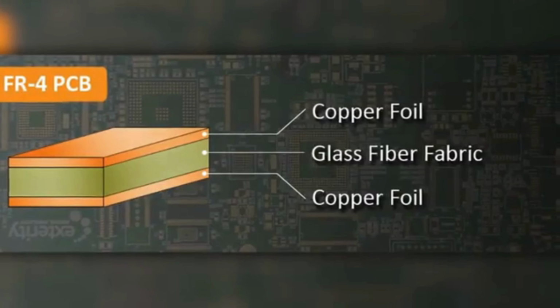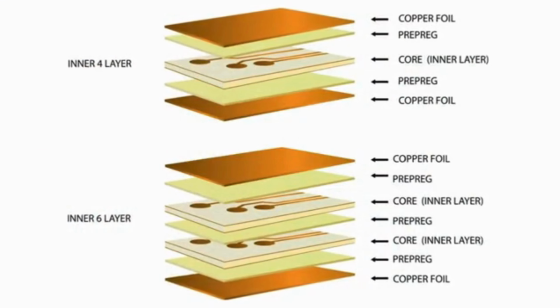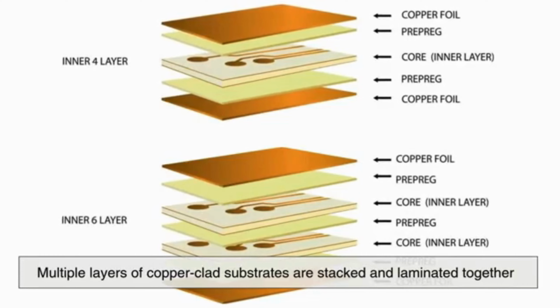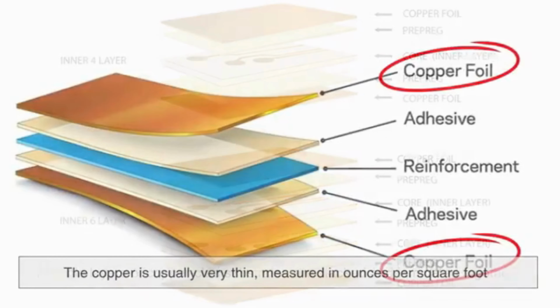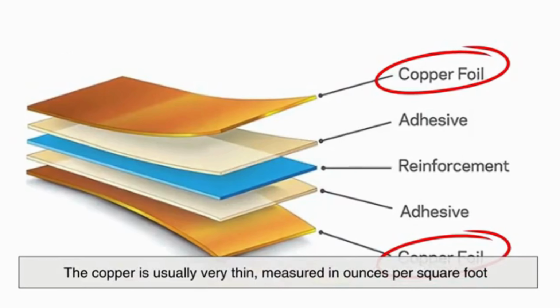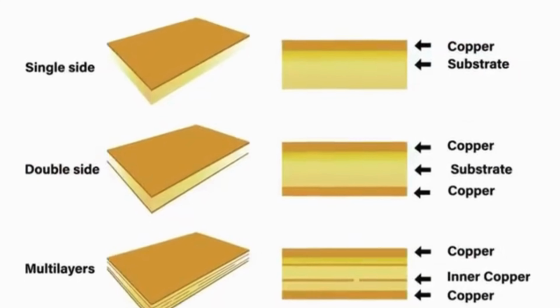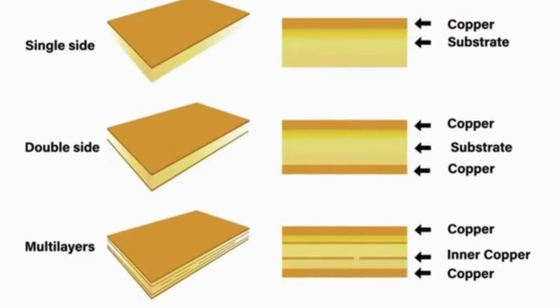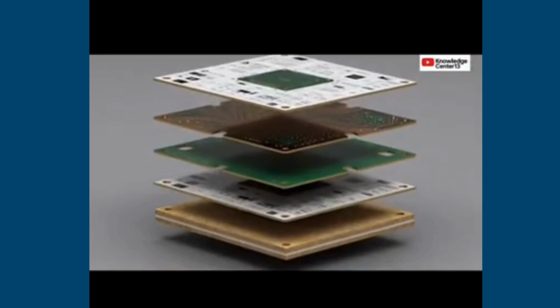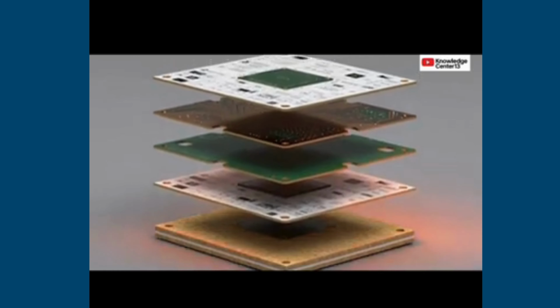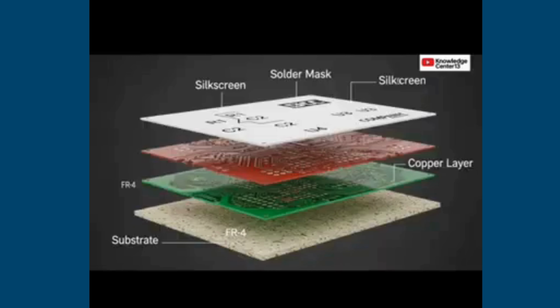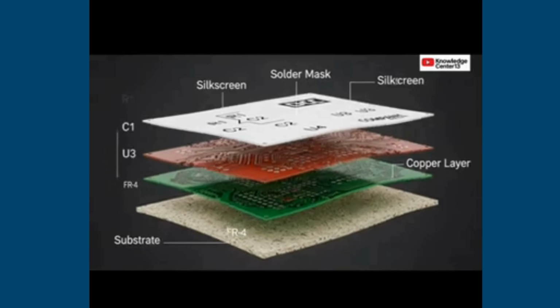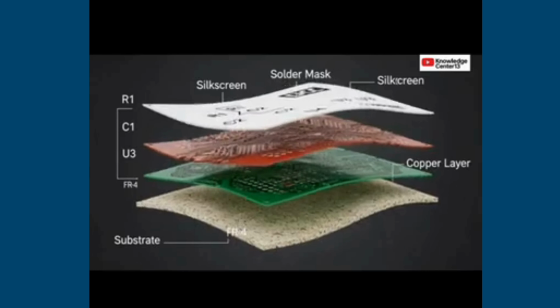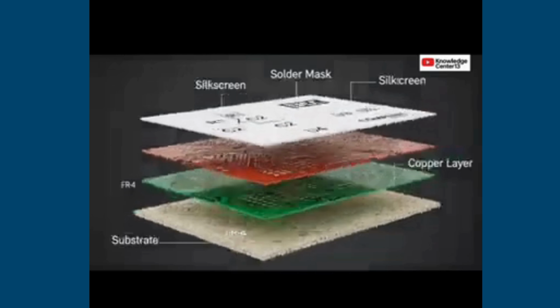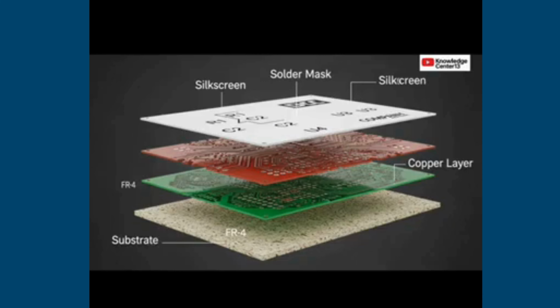FR4 remains the industry standard because it offers an excellent balance of high dielectric strength and electrical insulation, low dissipation factor, good mechanical strength and dimensional stability, thermal resistance and soldering durability, moisture resistance, and cost-effective large-scale manufacturing. Typical FR4 materials exhibit dielectric constants ranging from 4.0 to 4.8, glass transition temperatures, Tg, between 130 and 180 degrees Celsius, and excellent compatibility with multilayer fabrication processes.